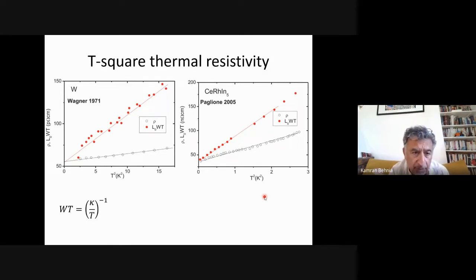People have measured thermal conductivity and compared the thermal resistivity with electrical resistivity. And what people find is that if you look at this thermal resistivity, which I call WT, you see thermal conductivity per se should go to 0 at 0 temperature because of the third law of thermodynamics. What's happening is that it can have a linear term. So if you take this thermal conductivity divided by temperature and invert it, you have a quantity which I'm going to call thermal resistivity. It is actually thermal resistivity times temperature, which can have a residual term and a slope. And the slope, very much like electrical resistivity, is T squared.